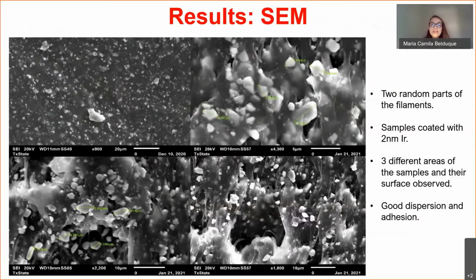These are the SEM analyses. We performed this analysis on the two composites processed with the twin screw extruder, with the objective of understanding the quality of dispersion of the fillers in the matrix. We cut two random parts of the filaments and coated them with a 2 nanometer layer of iridium with an ion sputter coater to improve the resolution. Three sides of the cross section of each sample and their surface were observed.